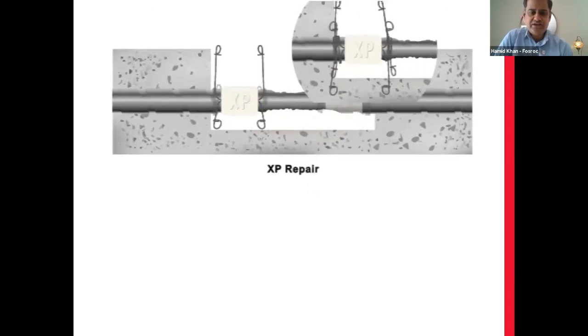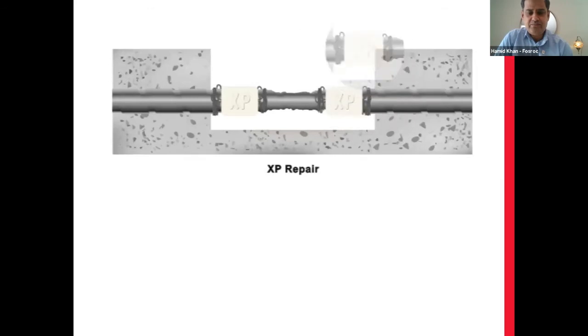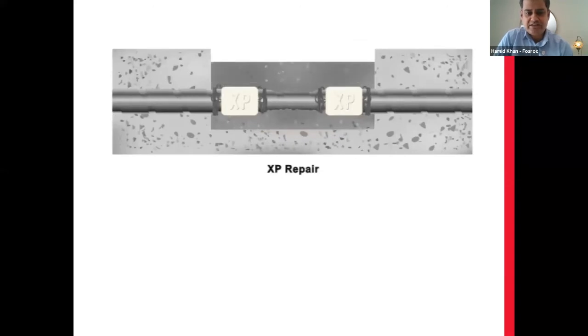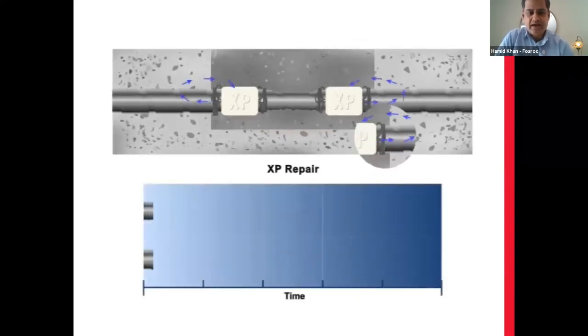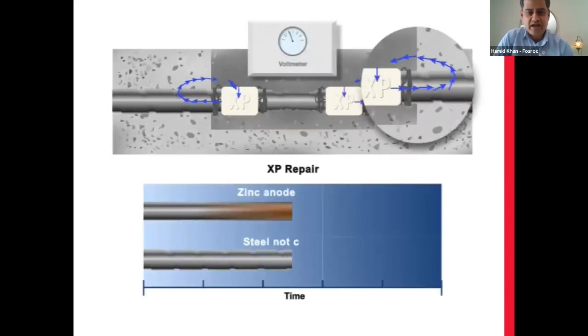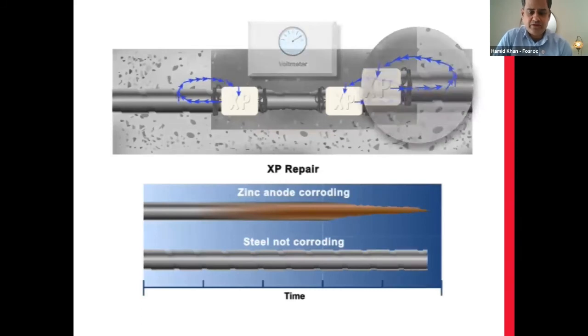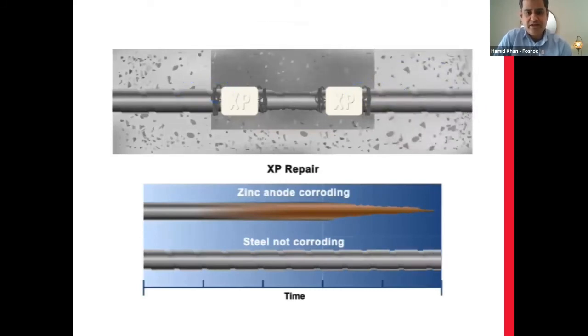So the solution is to have galvanic anodes at the perimeter, so that they not only protect the repaired area, but also protect against the incipient anode effect in the adjacent areas. And we could extend the life of the structure for quite a number of years. The electrochemical process will still occur, but it would occur in the zinc, which is surrounded by a highly alkaline mortar, the galvanic anode, and that will not expand as the concrete and the steel expand. So it is keeping steel as cathode because we are introducing an external anode body. This is also called the simplest form of cathodic protection, or galvanic protection.